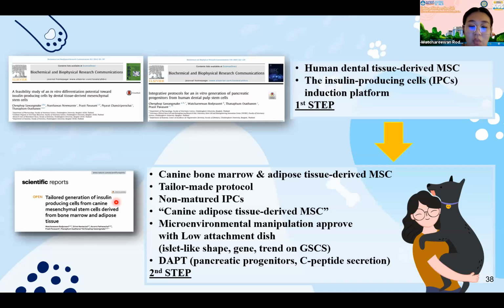For the canine, here we have two candidates: the canine bone marrow and the canine adipose mesenchymal stem cell. And we found that both mesenchymal stem cell types are able to produce the insulin-producing cell. However, each cell type requires a different protocol, which means that each requires a tailor-made protocol for itself. However, the IPC that we got is still non-mature, in that they cannot fully respond to the glucose when we trigger it. However, from this study, we found that the good candidate for the canine mesenchymal stem cell to choose for further study in the method development is the canine adipose mesenchymal stem cell, which is able to produce the IPC in a large number.